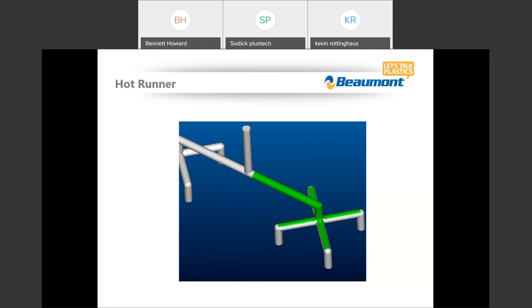Excellent. The last question I have here, unless we have a couple more come in: what is the impact of injection velocity? You know, fast fill versus slow fill. Very good question. The shear rate can depend upon the injection velocity dramatically. The faster you fill, the higher shear rates you get. You probably can see this very easily. Sometimes the easiest way to see this is with hot runner molds, because you can actually look at those temperatures jumping inside your manifolds at different zones, depending upon your injection velocity.